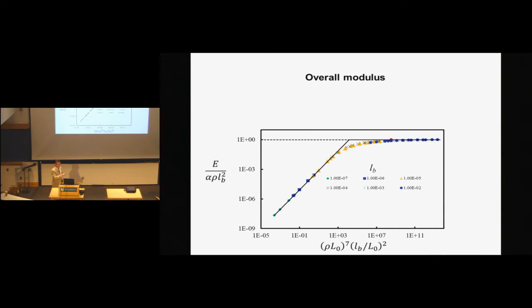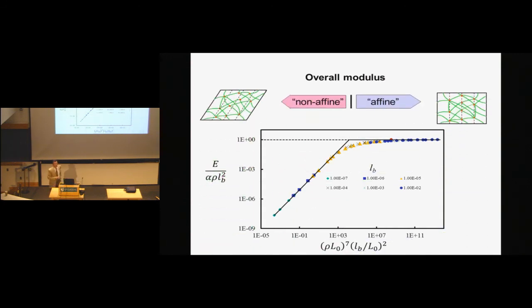So the stiffness of this material is extremely sensitive to density in this range, while it is much less sensitive in that range. It tells me that an organism which has a fiber network as the main constituent is able to add a little bit of matter to the network and change its stiffness by an order of magnitude. So that's already an interesting observation. Some other observation.